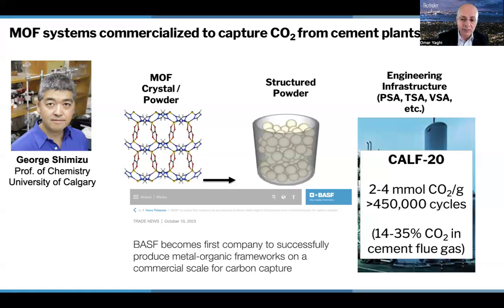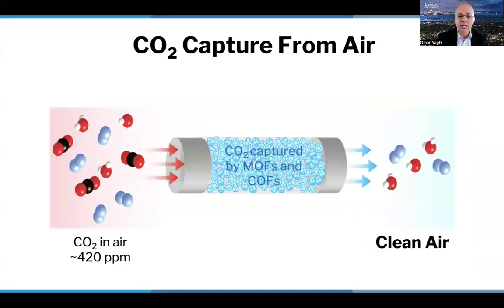But MOFs in general will not work for DAC, for CO2 capture from air. And the reason for that is that to do CO2 capture from air, you need the use of amines. And amines are basic, and most MOFs could not withstand long-term cycling in basic media. So this is basically the experiment that one needs to try when you have a material. Basically, you're exposing your MOF or COF to a stream of air that has CO2 in it. Obviously, this is 420 ppm, just like it is on average in the air, and see whether the material can scrub the CO2 out of the air and make air that does not have CO2 in it.